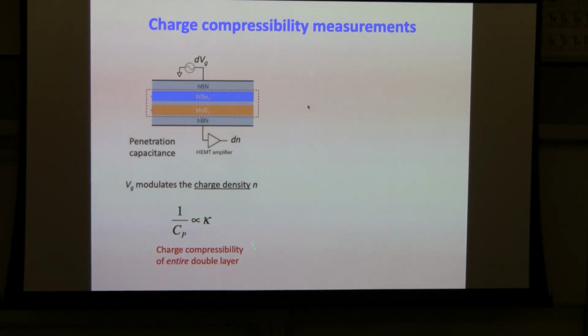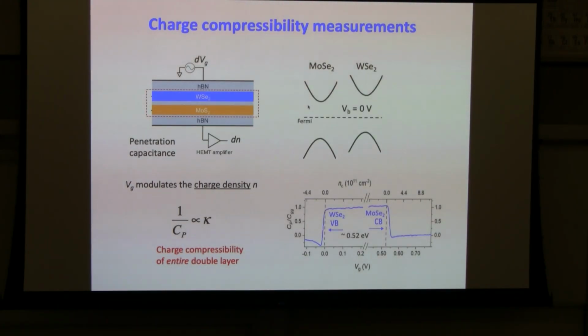And 1 over the penetration capacitance is actually proportional to the charge compressibility of the entire double layer structure within this red dashed line box. So this is the data under zero bias. The Fermi level is like this. With near zero gate voltage here, the Fermi level is inside the gap of the material. This double layer is actually a charge insulator. The electric field that you apply from the top gate would just easily penetrate through to the bottom gate, and you can collect the charge very easily. And so you get a large capacitance signal, which is actually close to the geometric capacitance of this structure here.